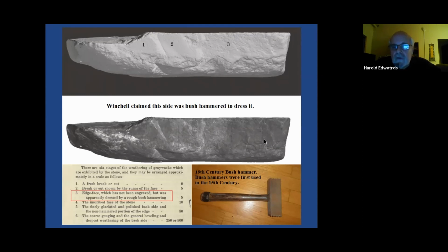It didn't first come into use until the 15th century. Another thing, if the bush hammer had existed in the 13th century and was used to hammer this rock, it would have micro-cracked it and subjected it to much more accelerated weathering, and this flat surface would not remain after 500 years. That was something that was found out in Prague, where after World War II, they had buildings made out of sandstone that were deteriorating, and they were